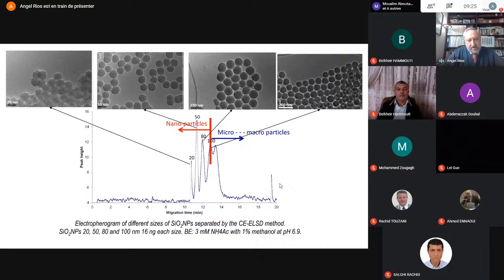We use, in this case, capillary electrophoresis coupled with evaporative light scattering detection in order, as you can see in the recording, to separate the different sizes of silica nanoparticles with very good resolution, as you can see on the left side of the recording, in order to check the presence of nanoparticles of different size. And of course, it's also possible to have some information about the presence of macro particles of this compound.